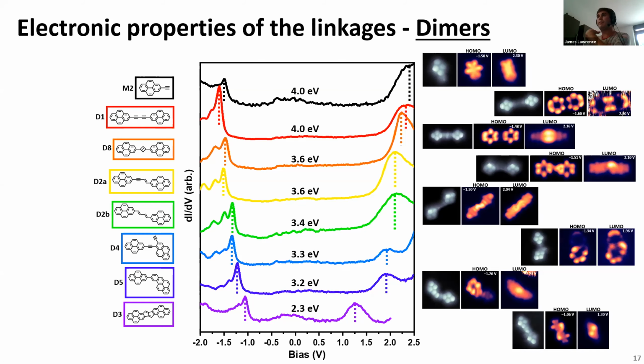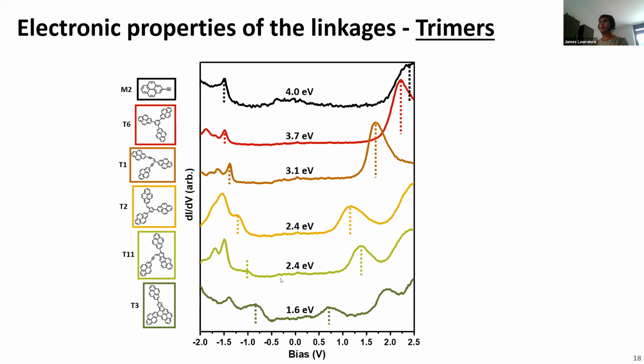So of course, we've got the same thing for trimers as well. Here are a few trimers shown here with their dI/dV spectra, again with a monomer shown for comparison. So again, you see a similar pattern where when you start forming, for example, double bonds or new rings, in particular rings that are fused to the pyrenes themselves, we get a dramatic reduction of the HOMO-LUMO gap.